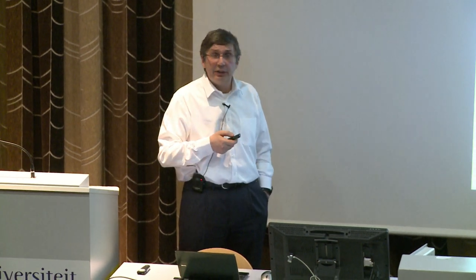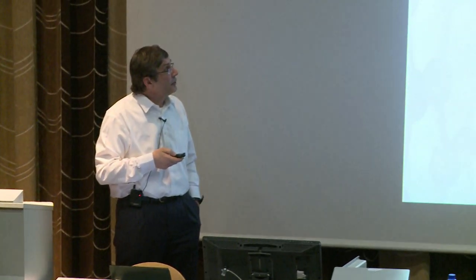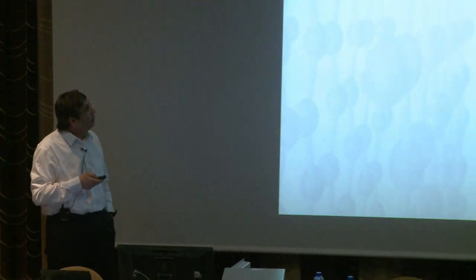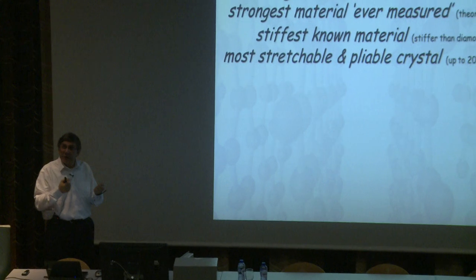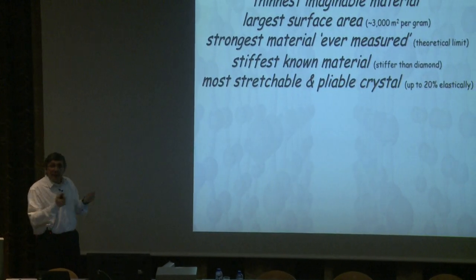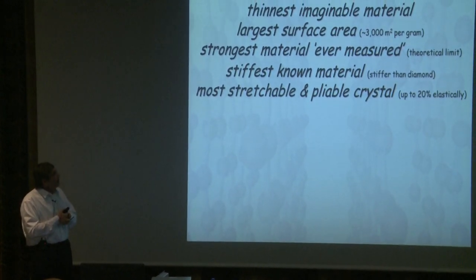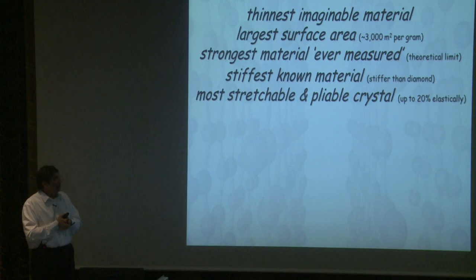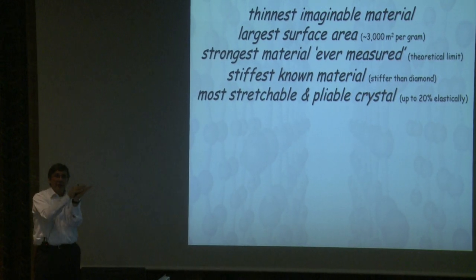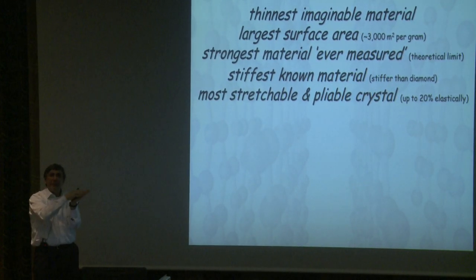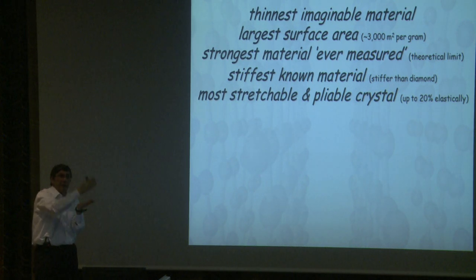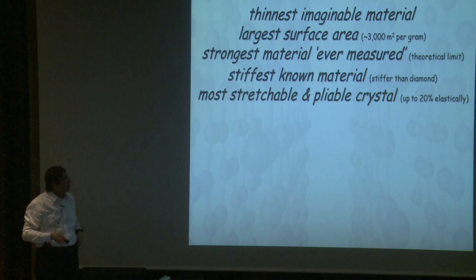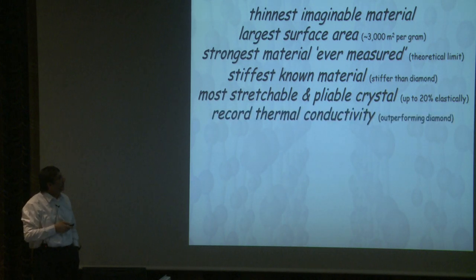It's stiffer than diamond, sort of 3 times stiffer. But try to stretch diamond, you crack it. Graphene is stretchable by 20%, and it's completely pliable. You can sort of bend it 90 degrees. Crystals would crack, but this crystal goes this way and another way without cracking. It's pliable material as well.